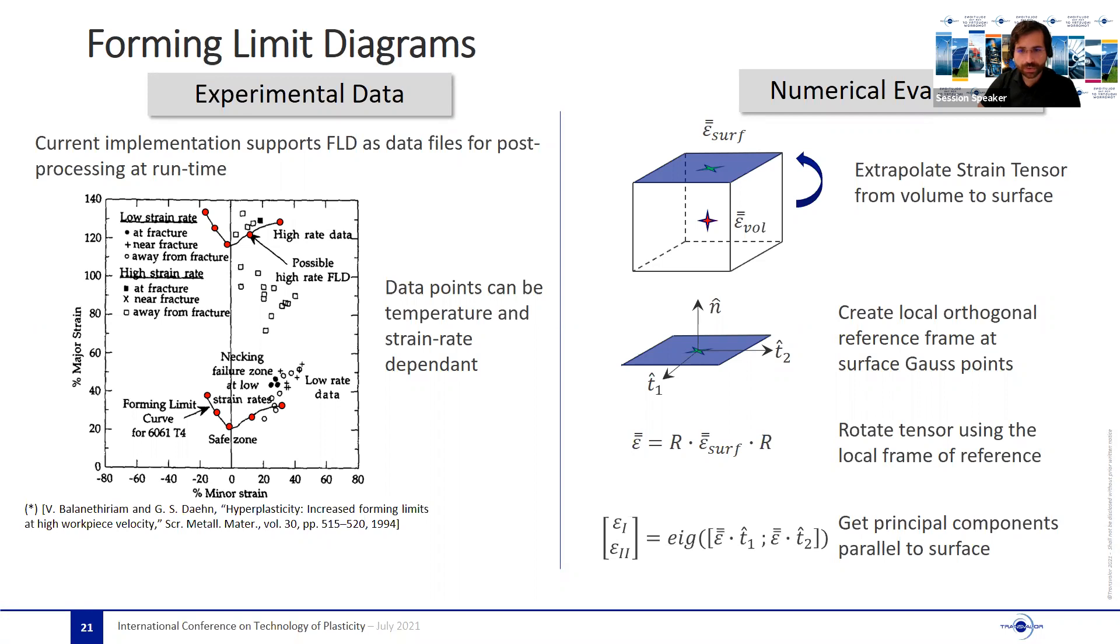When first introducing this technology in FORGE, I was confronted to the fact that most of the works found in literature regarding numerical simulations with FLDs are done on shell elements. Since FORGE is dedicated to bulk forming and the needs of our customers were to enable such analysis, but at the same time perform detailed study at the bulk of the material, I developed a technique to project the strain field computed at the volume points to the surface of the 3D model. This enables then approximating the same analysis done with a DIC system in which the surface strain field is captured by high-speed cameras and then transformed locally into a principal strain representation from where the FLDs are created.